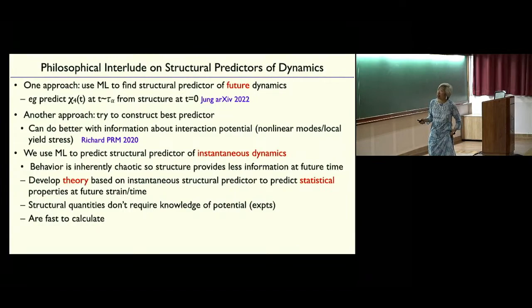Another approach that a lot of people have taken is to try to construct the best possible predictor of dynamics, whether it's structural or not. For example, they use information about the interaction potential. We don't want to do that, so we have stuck to purely structure, and let me explain why. The reason we want to just look at structure is that we can then deduce this in experiments. We have applied this to many experimental systems where we don't know the interactions. In colloidal experiments, you just don't know the interactions precisely enough to be able to calculate the Hessian. So that's why we want a structural predictor.